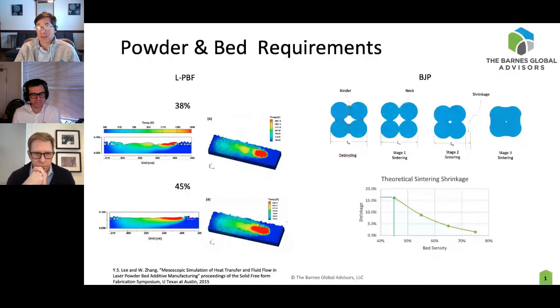The other thing I always think about is the classical powder metallurgy problem, where in order to get really good compaction densities in a classical die filling situation, you want a broad particle size distribution, so that the boulders make the shape, and then the medium-sized powders fill in between the boulders, and then the fine powders fill in between the medium-sized powders, so you have a pretty high density before you compress it. The same thing here in binder jet would be great. However, broad particle size distributions also don't flow well, and they make the driving force for sintering different, and you end up at a much higher temperature for your sintering, or a much longer time. Right.